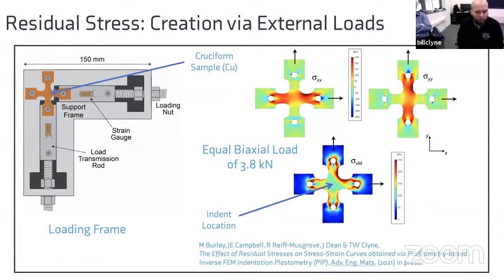The first of all are the Poisson effects from the contraction that change that area. That's a relatively small effect compared to the effect of having an effectively large cross-sectional area in these regions just due to the curvature that you have to have on the arms. Now, what that leads to, if we simulate this relatively simple case, is that the stress in the arms here in the X direction and here in the Y direction, if we apply the same load in both directions, we'll see symmetric effects in the X and Y stresses. But you can see that the stress is quite a lot higher in the arm than it is in the center.